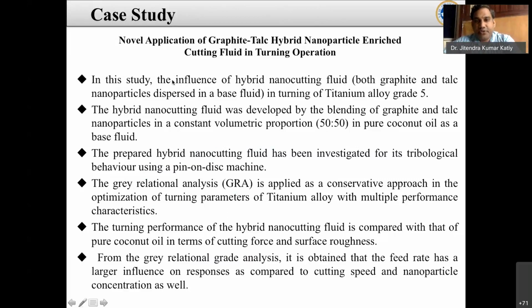So in this study, I just use graphite and talc nanoparticles, and we mix them with coconut oil. According to this, vegetable oils have less fatty acid and all the things are organic, so they can provide better lubricity properties than mineral oil and synthetic oils. We use coconut oil because in the southern region coconut is easily available as a cutting fluid, and I performed this on titanium grade 5, which is used in medical applications. I developed this at 50-50% volume concentration of nanoparticles.